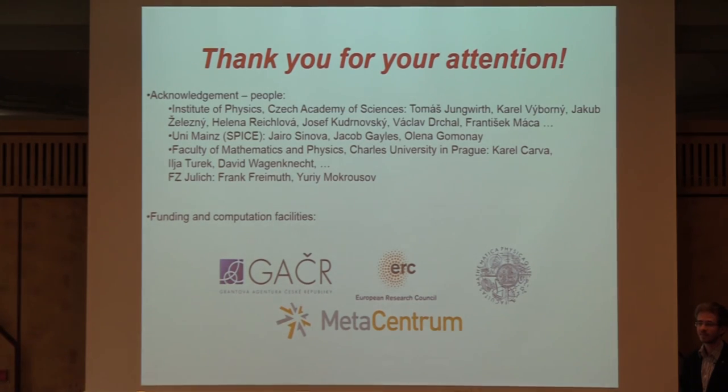If I may comment on this, I think there's also another factor: in Dirac semimetals you need a specific symmetry to protect the crossing, while in Weyl semimetals the crossing is protected against any perturbation which doesn't break translation symmetry. So I think this is another advantage of the Dirac semimetals, because by rotating the magnetic order you can break the symmetry which protects the crossing. In Weyl semimetals this probably is not possible. Okay, you are essentially more protected, which usually people say is a good thing, but in this case we are actually glad that we can break this protection. But I have one answer, that it's possible from a symmetry point of view to break even Weyl points. So this mechanism is possible to affect them.